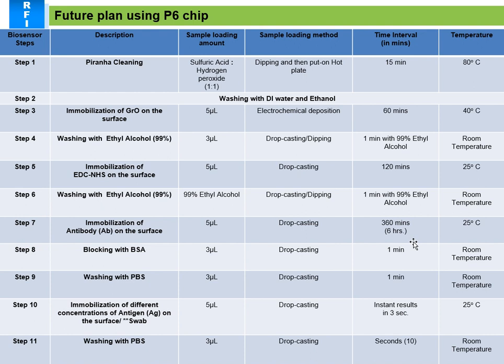So in this step I have to use the electrochemical machine for the deposition of graphene oxide, and I have done 20 cycles, and I know it's a thick deposition of graphene oxide. Afterwards I have to wash with ethanol, or ethyl alcohol, and then I immobilize the EDC-NHS. Until today I just immobilized EDC-NHS and washed with ethanol.